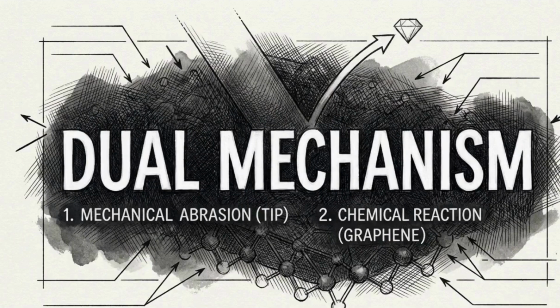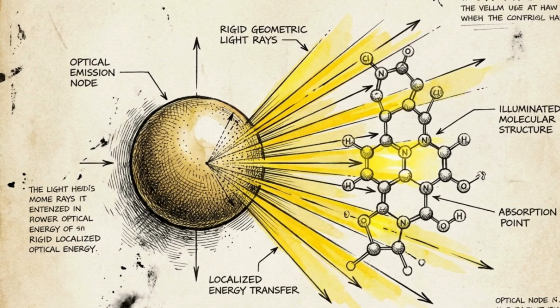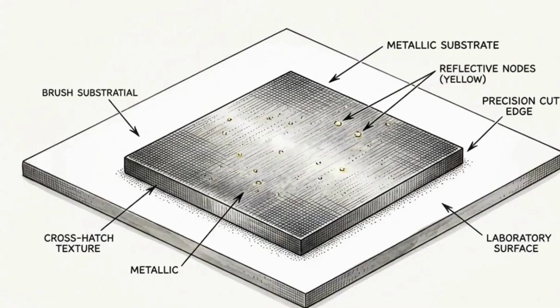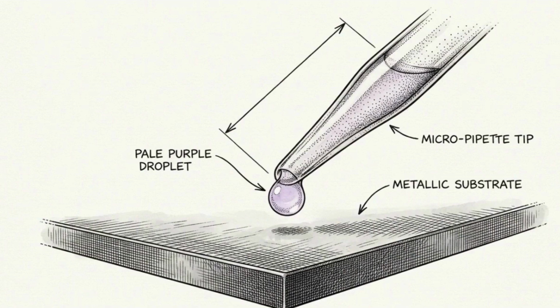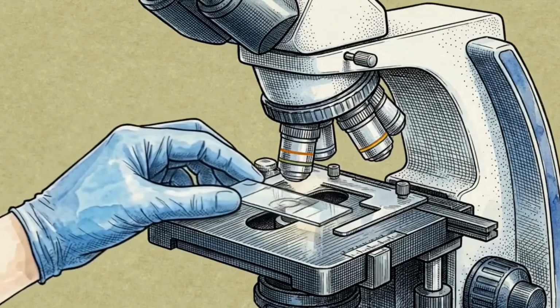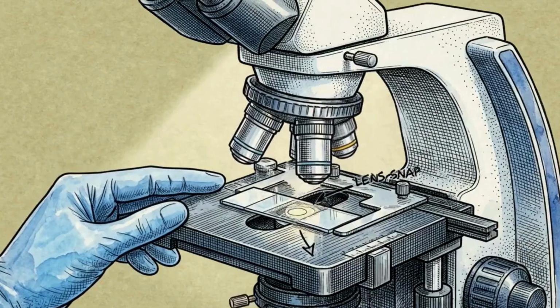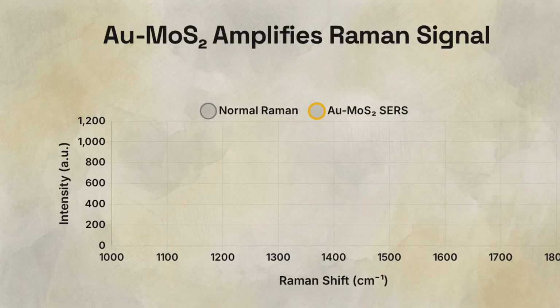The extreme sensitivity of the substrate relies entirely on this synergy. The gold generates an intense localized optical field to illuminate the molecule, while the engineered MoS2 provides the physical bridge for rapid electron exchange, magnifying the vibrational scattering. To validate the physics of this dual mechanism, the Au-MoS2 substrate is tested against an analyte. Crystal violet is reintroduced, this time at extremely low trace concentrations. The dilute liquid is drop-casted directly onto the hybrid substrate, allowed to settle, and then placed under the focal point of a Raman microscope. This chart compares the resulting SERS spectra against a normal Raman reading of the exact same molecule. The difference is immediate.